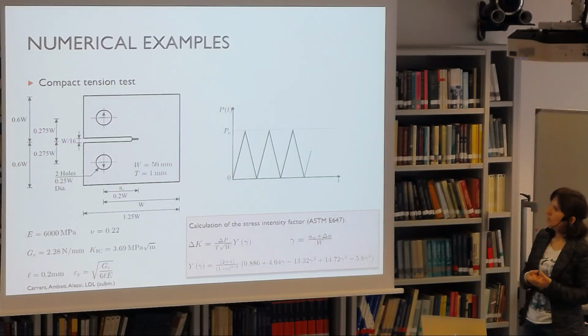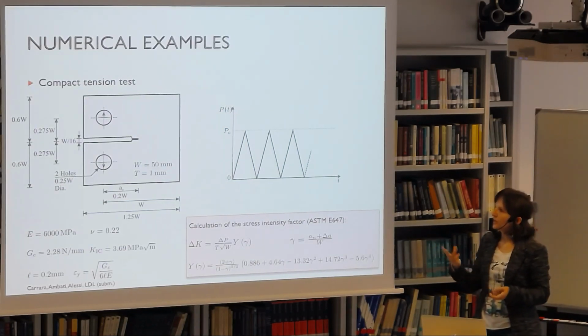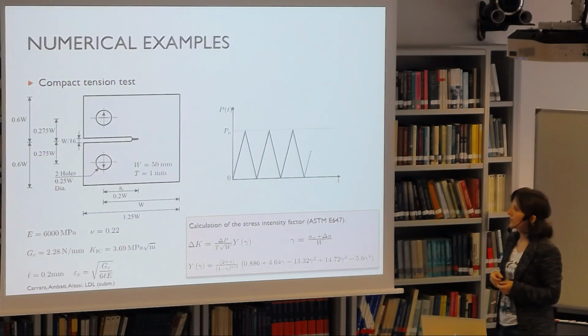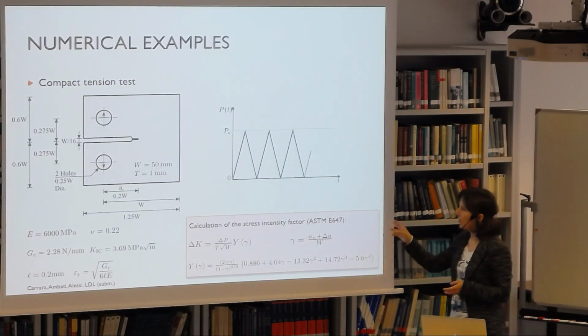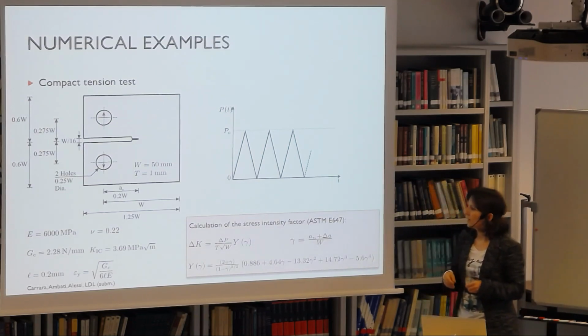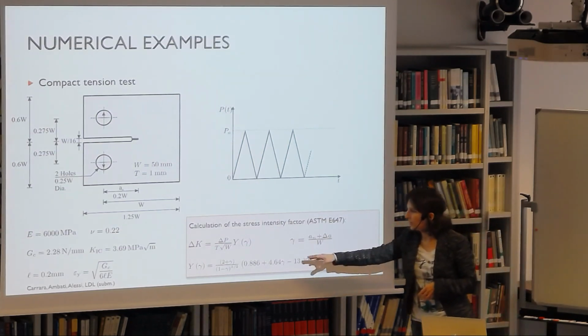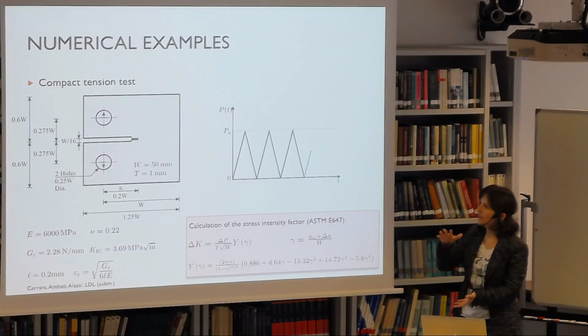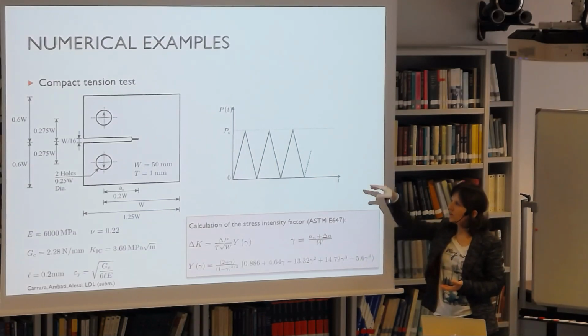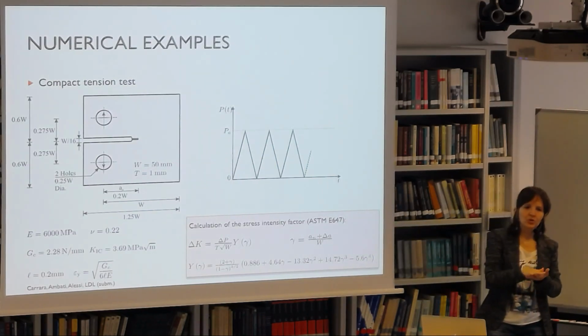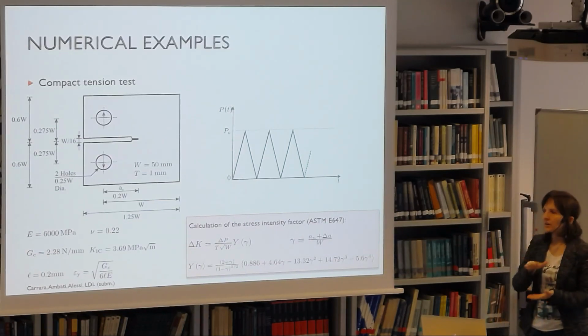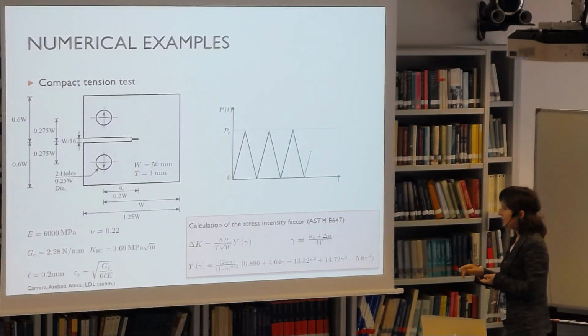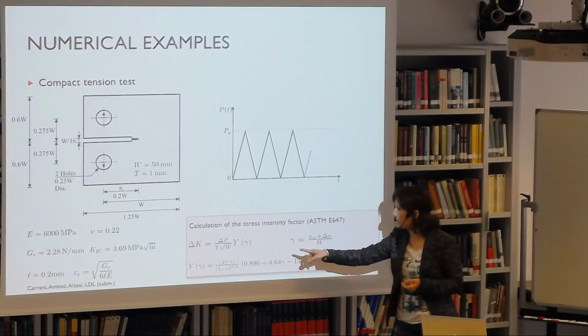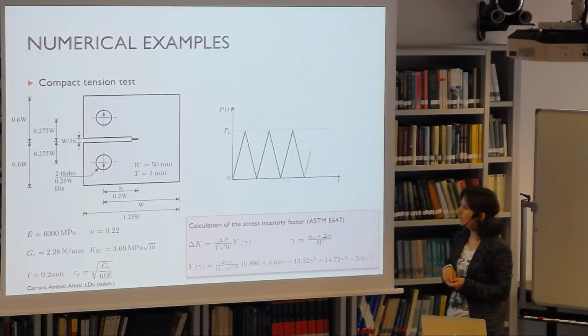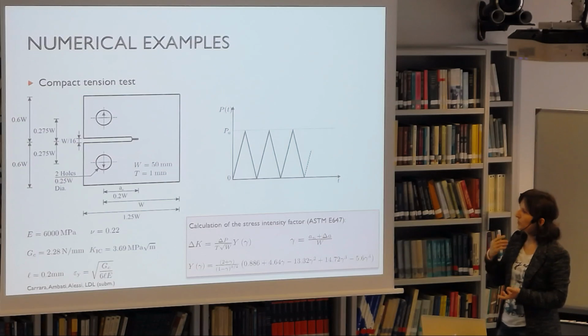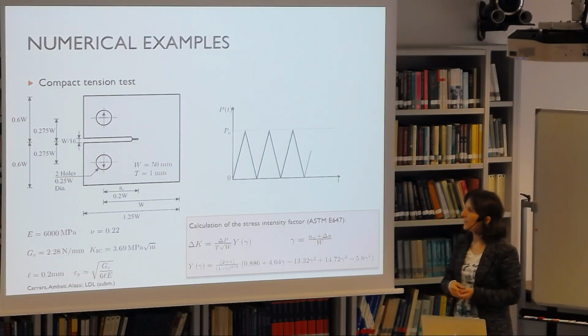And to do this, we chose a very typical type of specimen, the compact tension test that has an ASTM norm, so we follow the norm. And for this ASTM norm, we know exactly how to compute delta K. Delta K would be, for a cycle, the amplitude of the stress intensity factor during the cycle. And of course, during cycling, we are also updating the length of the crack, so delta K is computed always on the current crack length.